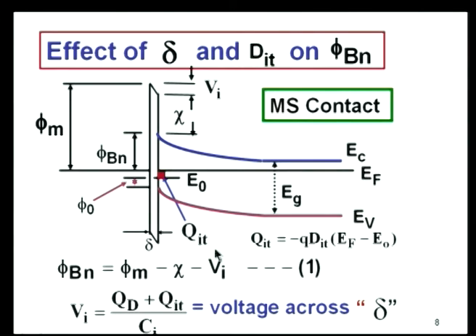Okay. So, if QD is negative, the drop will be minus here and plus here. So, the field will be in the opposite direction, upward. That is taken care of by the sign. So, substitute for this V I as minus Q D I T E F minus E naught by C I. So, what we are looking at is what is phi B n now?